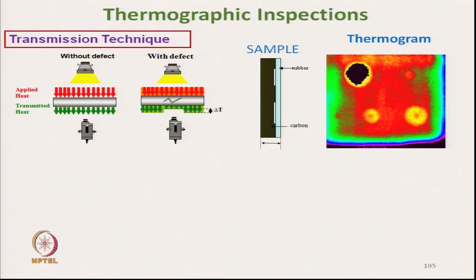And this is the heat source, heat is applied to the sample with a defect. Here, due to the presence of a defect like a crack or any other thing, the heat transmitted to the other side will be non-uniform, and by using the thermal imaging camera we can take an image of the temperature distribution on the other side, and here this is showing the image on the other side, and this shows the defect present in the composite.